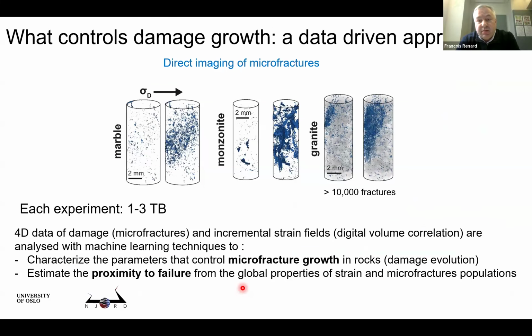And the question we will ask is, if we have an image of a rock sample like that, where more or less we know all the damage in 3D, can we predict the distance to failure or the proximity to failure? So intuitively, a sample with more damage will be closer to failure. But how much? Each experiment is between 1 and 3 terabytes. I think now we have more than 40 in 8 years of experiments on the synchrotron. And I will mainly show you results of experiments on 8 samples that we have studied over the years. 8 samples times, let's say 2, it's 16 terabytes, and with 16 terabytes, how to dig into this data, that's how we had this idea to use machine learning.